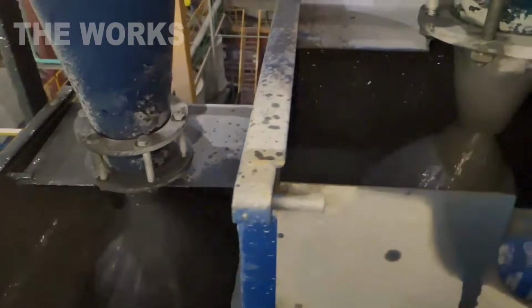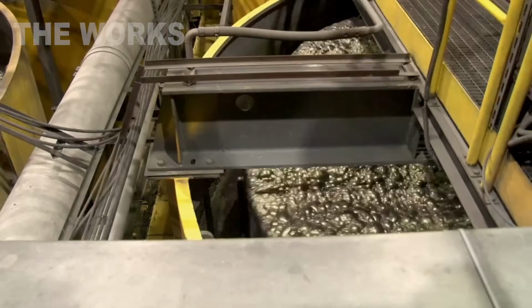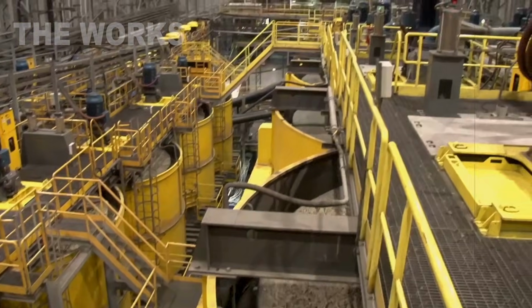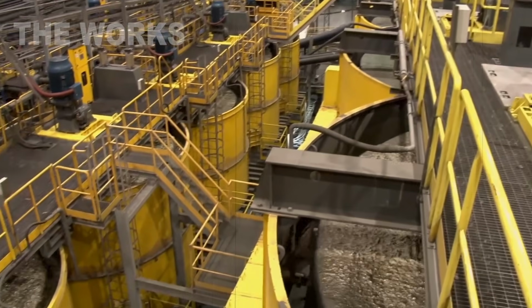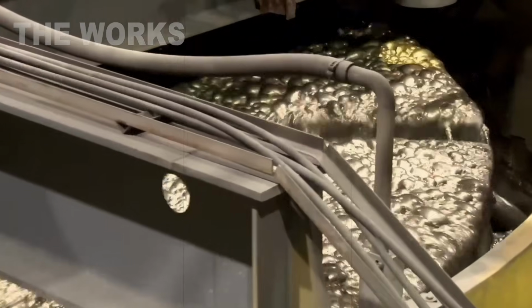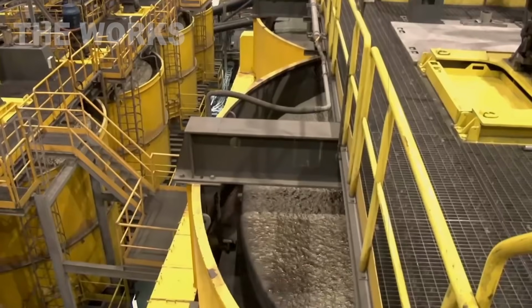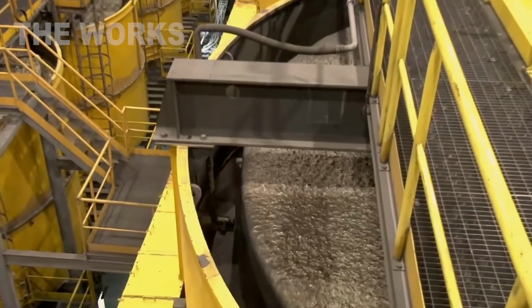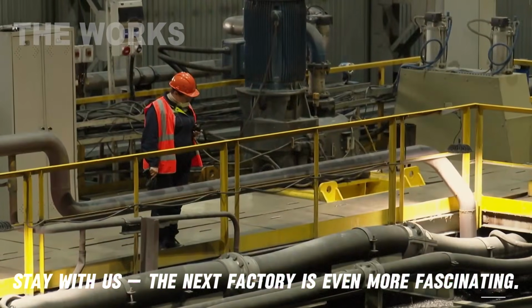These reagents selectively attach to tungsten mineral particles, making them water repellent. Air is then pumped through the mixture, creating millions of tiny bubbles. The tungsten mineral particles latch onto these bubbles and rise to the surface, forming a foam. Other unwanted minerals stay at the bottom. This enriched foam is collected. These processes yield a concentrate containing 60 to 70% tungsten trioxide, which is an intermediate form.